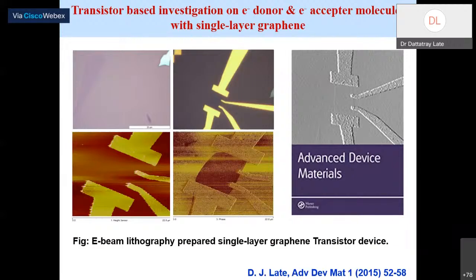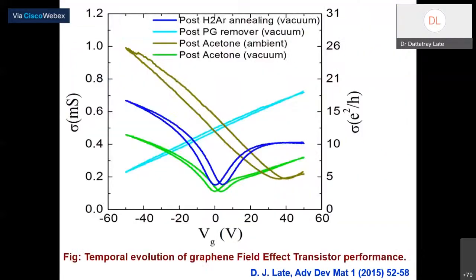For example, like this. This is just before coating, exactly left, and this is after you prepared the device using electron beam lithography, and this is the scanning electron microscope image, and the optical image below is the AFM image of that same device prepared. So the experiment we have done here is very important. We have tested the device with various parameters, like just prepared device, device kept in vacuum, device post annealed with acetone, and many others. The natural device, because graphene is single layer, is ambipolar in nature. So when we apply a positive gate voltage or negative gate voltage, it gives the ambipolar characteristics which we have found in our device.